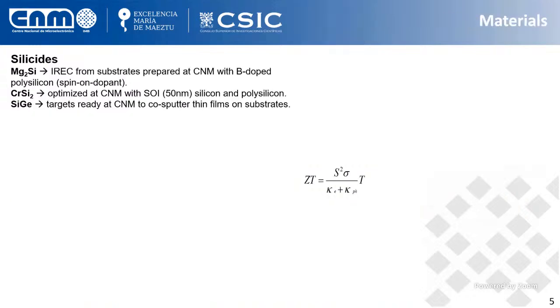Silicides. What are they? Previously it was already mentioned this ZT figure of merit, which is the Seebeck coefficient of the material, the electrical conductivity, and the thermal conductivity on the bottom. We're working on mainly 3 different silicides. Silicides are just silicon alloyed with different materials. Typically in the literature, when they are used for thermoelectrics, they are using magnesium silicide or chromium silicide, which are, let's say, the in between of the most performing and something that is CMOS integratable or compatible with what we are doing at the clean room.